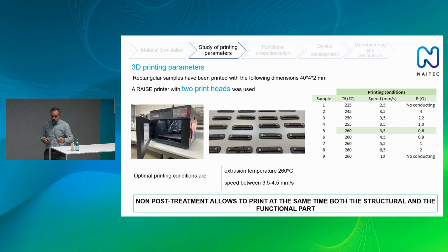Another approach is to load the filament with a lot of metal particles and then remove the polymer with a high temperature process or whatever. But then you can only print one material, or at least all the materials that you print need to resist this thermal treatment. So in our case, the idea is that we can print this material, and it's already conductive, together with the base polymer, so that the electronic devices have also the conductive part embedded into the structural part.